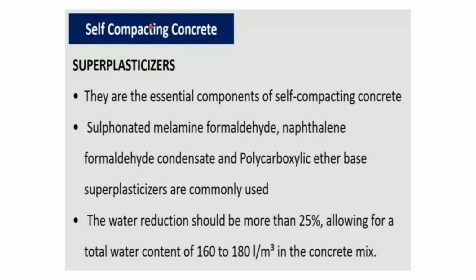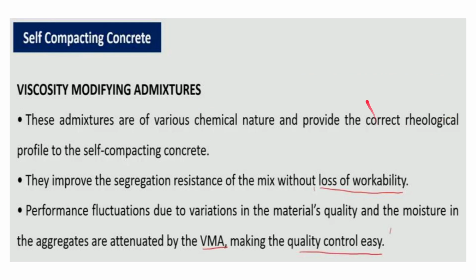Now let us go to superplasticizers. Superplasticizers are an essential component of self-compacting concrete. Some of the very common and famous ones are sulfonated melamine formaldehyde, naphthalene formaldehyde condensate, and polycarboxylic ether base. These are used by the construction industry. The water reduction should be more than 25%, which also helps in reducing the cement content. That allows for a total water content between 160 to 180 liters per cubic meter in the concrete mix. So this is an ideal value.